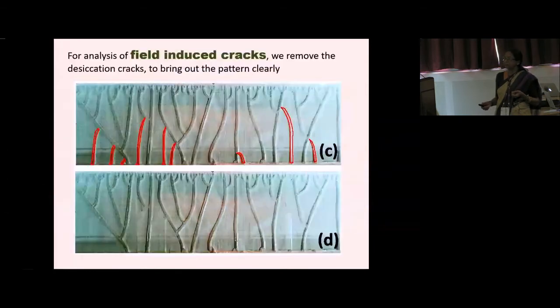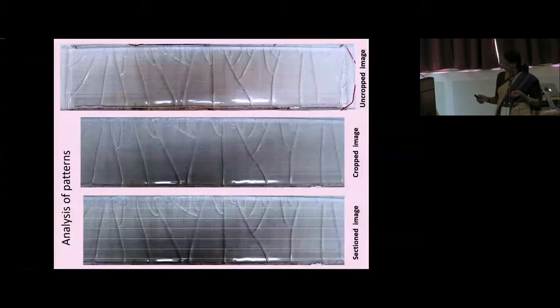So what we did is, before the analysis, we marked out the desiccation cracks, pure desiccation cracks, and we artificially removed these. So this is the pattern we are going to analyze. Now, these are the steps of how we are doing the analysis. This is the full image. We have the edges cropped, as I explained already. And because the number of cracks is going down as we go from positive to negative end, we have divided the system into 7 parallel segments, and we measure the length of cracks in each of these segments and see how that is changing.